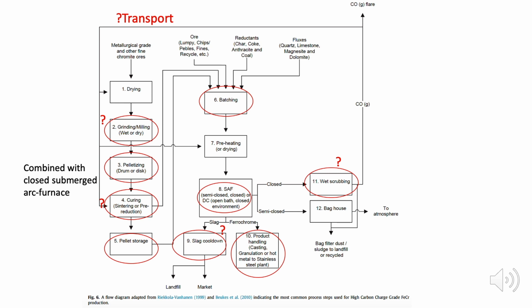Bag filter dust typically contains the highest concentrations of chromium-6, while the slag forms the largest amount created by volume. The chromium content in slag is between 2 and 12%, present in oxide and metallic forms. Very significant quantities of ferrochrome wastes are generated and discarded in dumps.